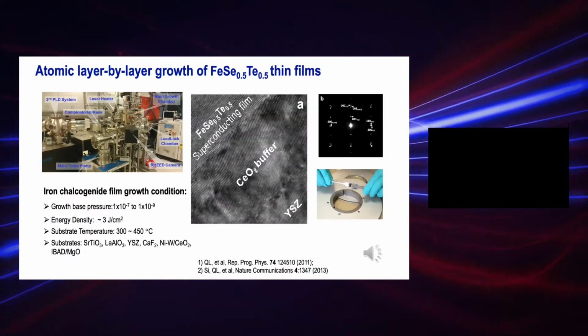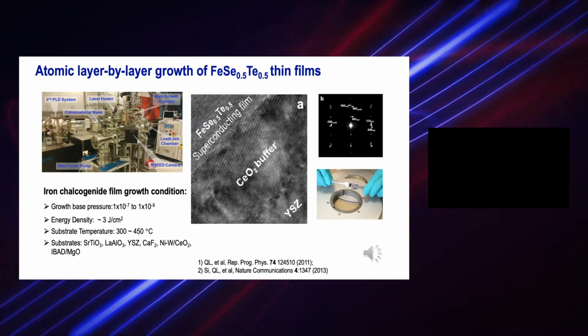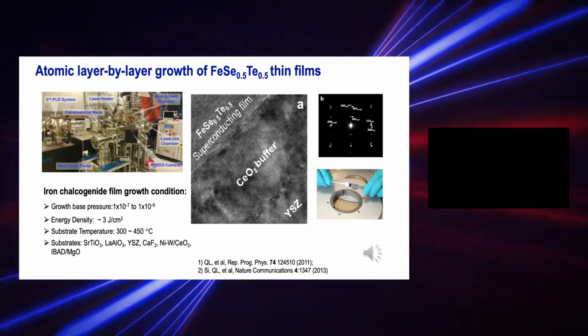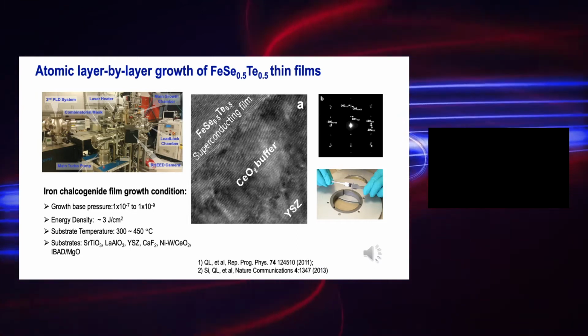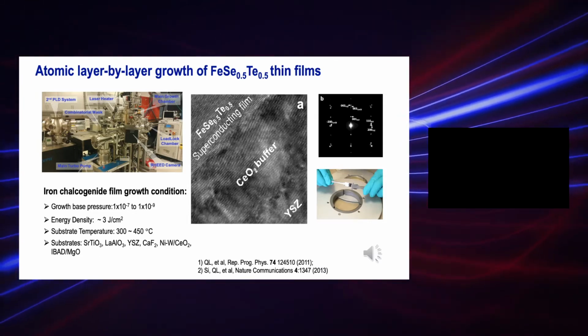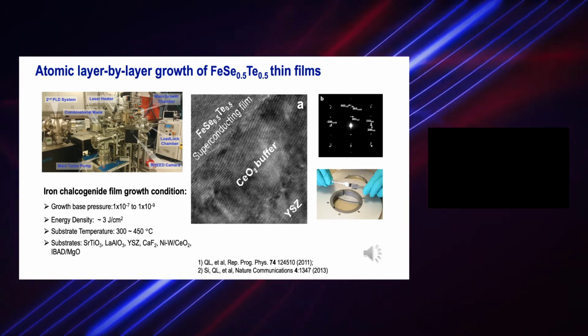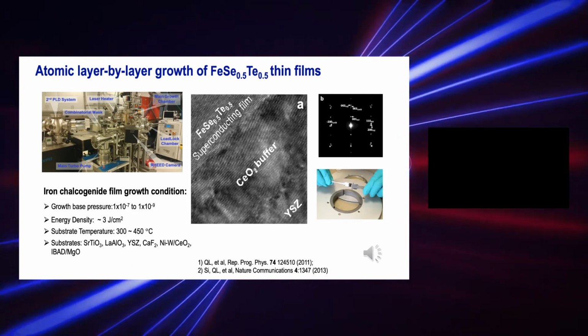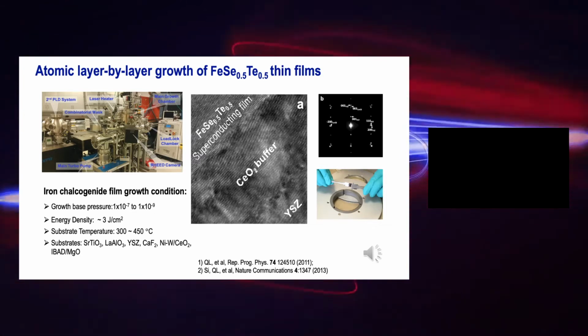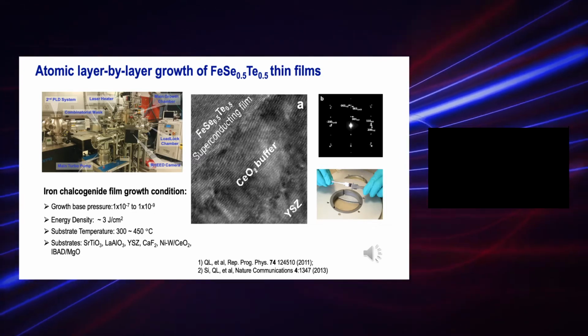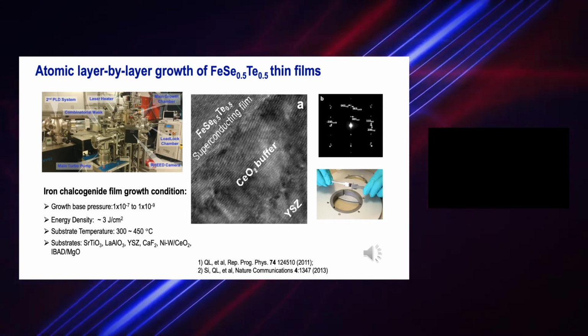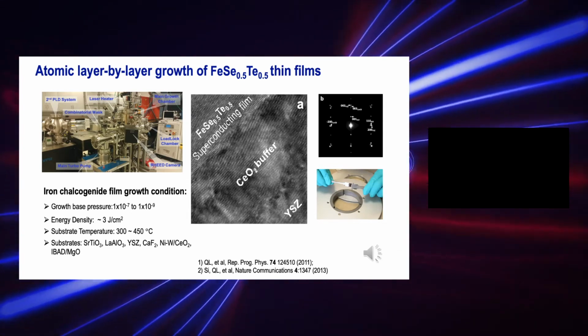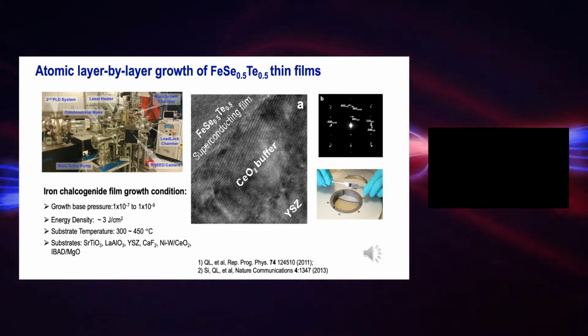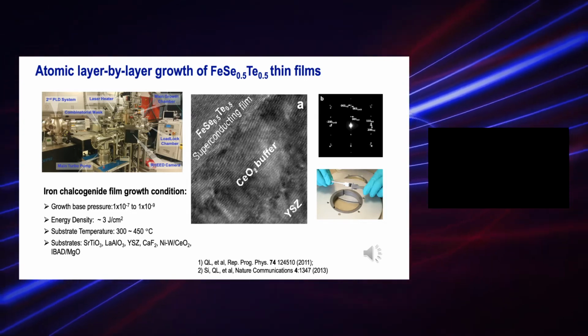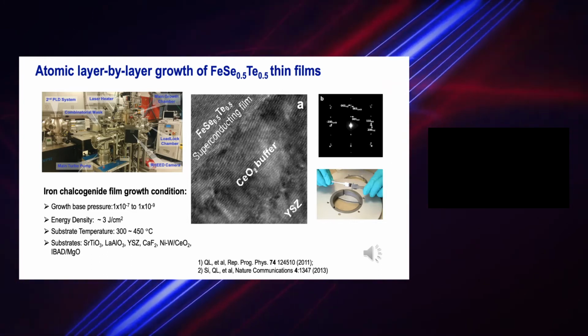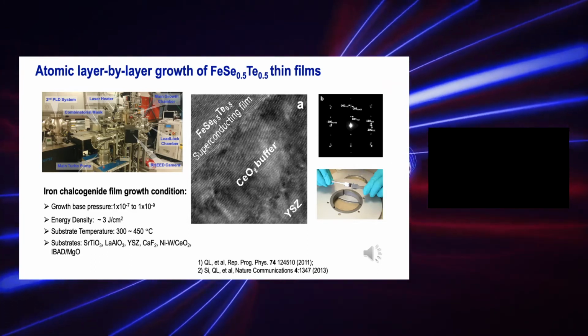At Brookhaven, we have two thin film growth chambers. One is the older one, the generic pulsed laser deposition system, PLD system. The newer one is an MBE-type chamber, where you can go to UHV, allowing us to grow atomic layer by layer films of iron chalcogenides. In the middle part of the image, it shows the TEM cross-section of the film grown on YSZ with a cerium oxide buffer. Later we found that when we use a cerium oxide buffer, films generally have a better quality.